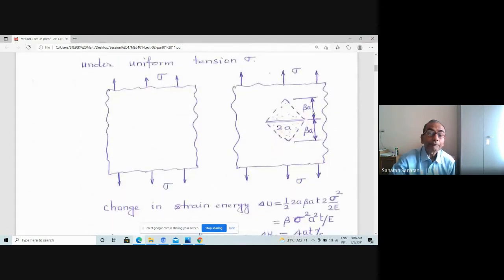So what happens is, if you take a flawless plate, then you have stress sigma everywhere. If you have a defect inside the material of size 2a, and you are pulling the material, it is logical to expect that the material above and below the crack becomes a shadow region. It does not get loaded. When you have a plate without any crack, it is uniformly stressed everywhere. But when you have a plate with a crack and it's loaded, it has some area which becomes a shadow area. There is no loading on it.